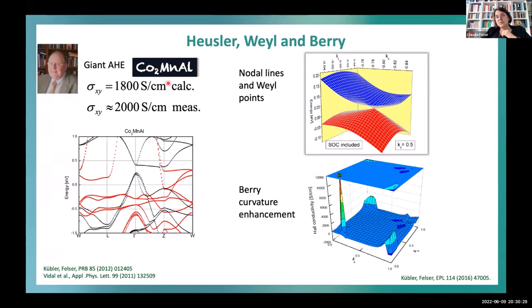And at this time, we looked at cobalt manganese aluminium. Going back a few years later, we recognized, okay, we have Weyl points in this compound, and this is responsible for the giant enhancement of the Berry curvature, which leads to this giant effect, which maybe makes this material even interesting for Hall sensors.